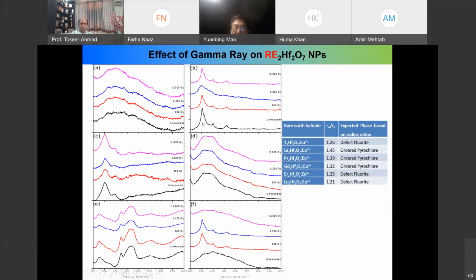but there are a couple of samples, for example, this lanthanum hafnate, which initially is a pyrochlore structure. At this dose, it looks like it becomes the fluorite structure. And then with a higher dose, it becomes the pyrochlore again. And for this one, this is the lutetium hafnate, which is the opposite. It's a fluorite structure at this dose, and then it becomes a pyrochlore structure, and then at a higher dose it becomes the fluorite structure again. But for the other ones, it doesn't change that much.